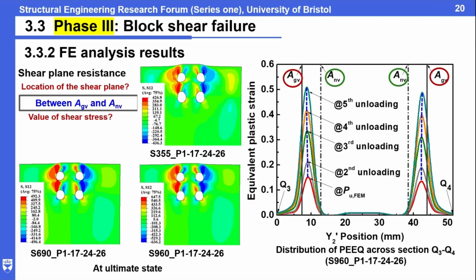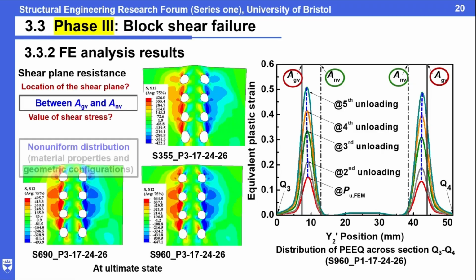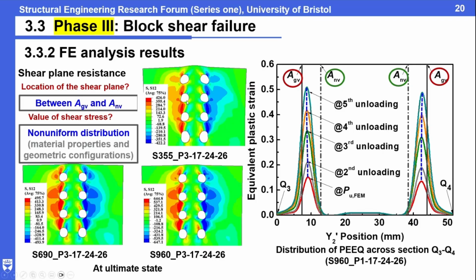So we don't know. This is the 3 just with the 2 rows of the bolt. We found that at the ultimate state, it seems like it can be fully developed. And if we look further from the 2 bolt row extended to the 4 bolt row, we will find that nearly at the end, actually the shear cannot redistribute fully at the ultimate state. It means you cannot just consider it's 0.6 Fu already, or just ignore the strain hardening and think about its 0.6 Fy already. So we need further investigation.